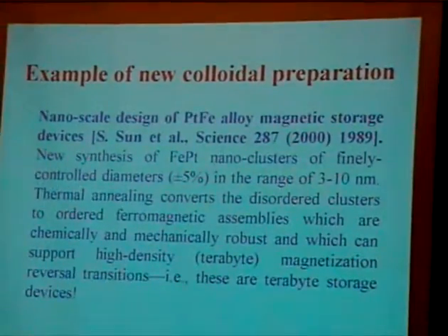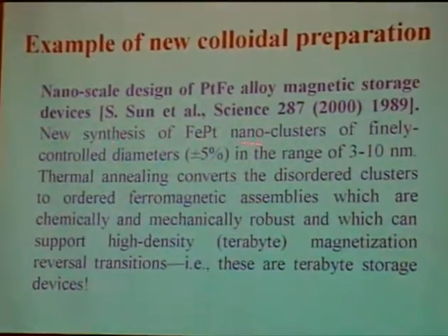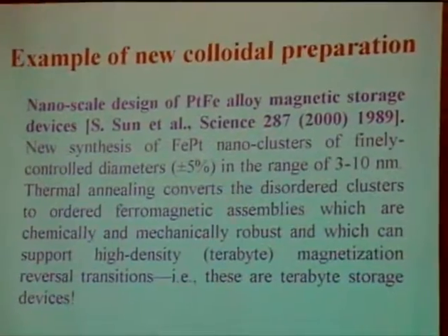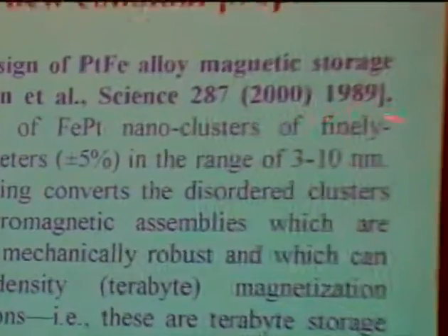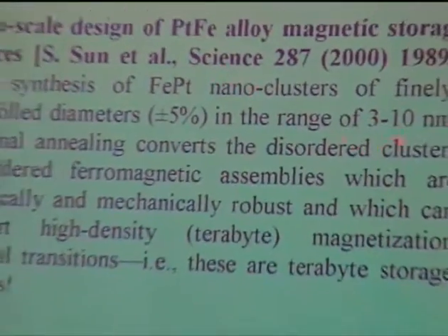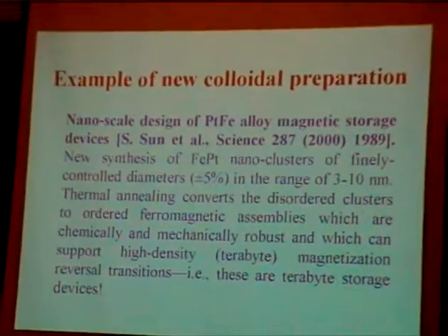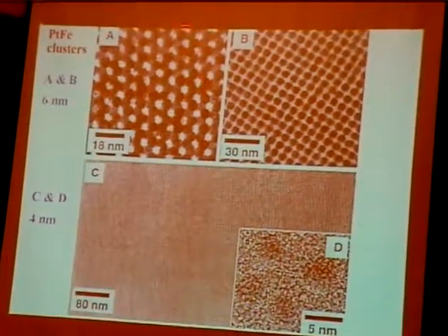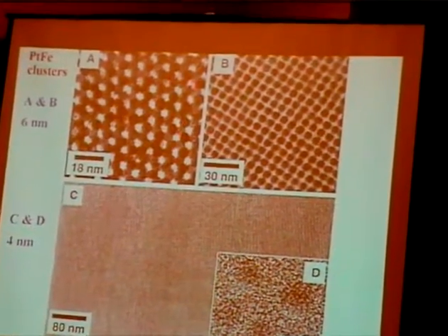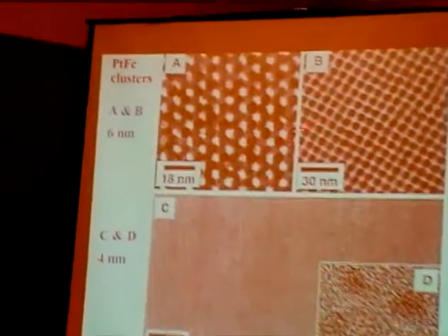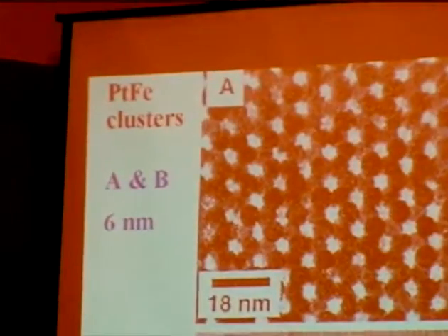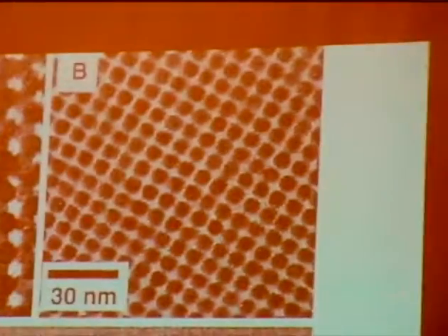An example of a new colloidal preparation is the work of Sun et al., reported in Science, where they described a new synthesis of iron-platinum nanoclusters on silica having finely controlled diameters, plus or minus 5%, in the range of 3 to 10 nanometers. We see some of those on the next slide. Here are the 6 nanometer clusters - you can see that they're uniformly sized and distributed. These are 4 nanometer clusters from their HRTEM.